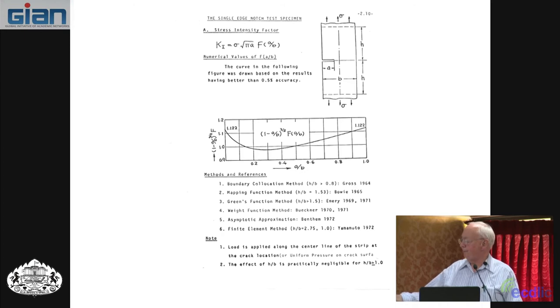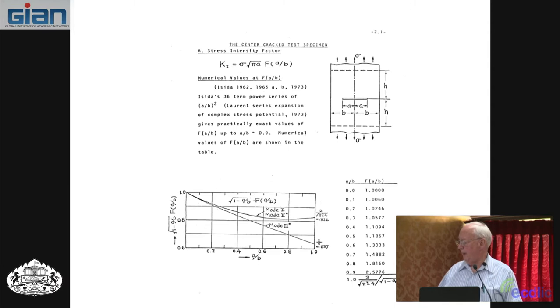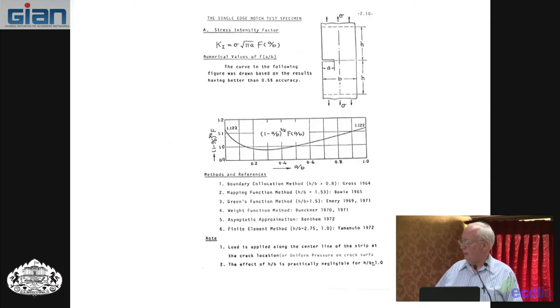In an edge crack, when you have a very short crack and this tends towards zero, in the limit, capital F tends towards 1.122. So cutting it down the middle relaxes that line and causes the K to go up a little bit. The other thing to point out is that whereas this has a table, this does not have a table, but rather just a graph. That graph is a little bit hard for some students to use because it's normalized. The reason it's normalized is to make this curve flatter. If you don't normalize it, it would go off to very high numbers quickly, but with it normalized, it's much flatter.